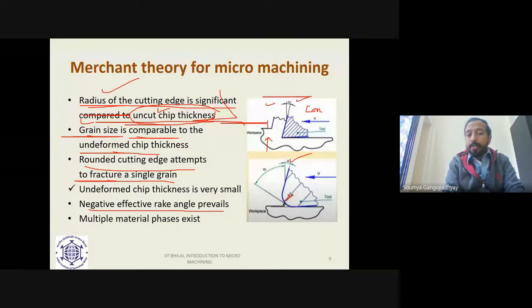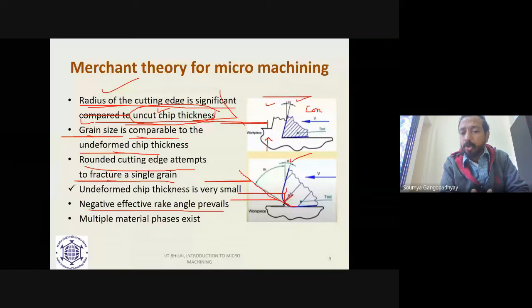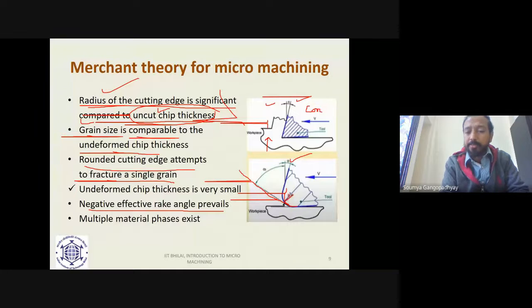But when you are considering this high edge radius, see, this is the effective rake angle. And this effective rake angle becomes highly negative. And what is the repercussion? What is the implication of the highly negative effective rake angle? High cutting force. You know it very well. When the rake angle becomes more positive, cutting force is less. When the rake angle becomes higher and higher on the negative side, cutting force becomes more. But then it strengthens the tool, but that is a different issue. But then cutting force is high. Energy will be high. Specific cutting energy will be high.